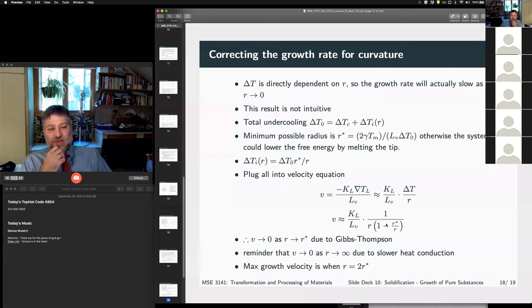Because we know that if the tip radius gets smaller than R star, it's just going to dissolve back away. It's going to melt again, right? Because the system can lower the Gibbs free energy by turning that cluster back into liquid, right? So R star is the minimum possible radius, again, due to Gibbs-Thompson from our nucleation theory. So as R goes to R star, our velocity has to go to zero, right? And as R goes to infinity, our velocity also goes to zero because of the poor heat conduction, right? And if you play with this, you see that the maximum growth velocity happens when the radius equals 2R star, right?